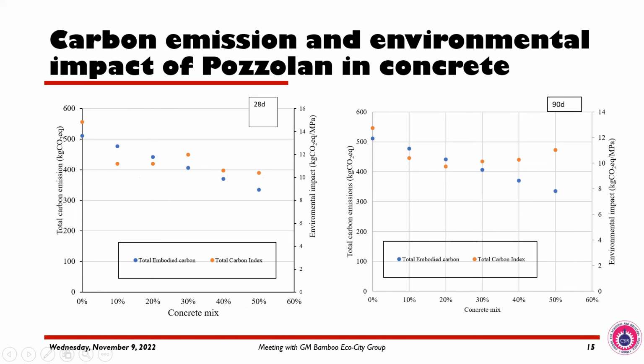Right. So it means that we have an appreciable environmental impact at 30% than the 40%. At 90 days too, there was a strange thing that happened. At 90 days, at 50% of my replacement, I have a very high environmental impact. So it means that when you cure your material more than 28 days, to 50 days and 90 days, you are achieving a higher environmental impact as compared to this. So the key thing that is important here is that as building professionals, do we settle on 28 days as the main time of curing if we really are thinking about carbon emissions and environmental impact?